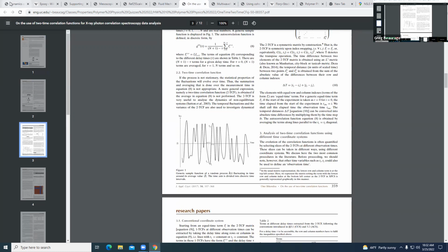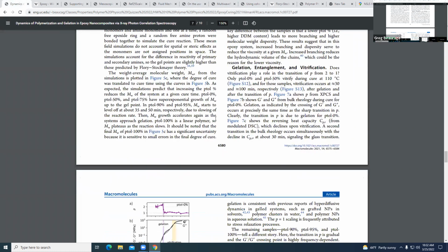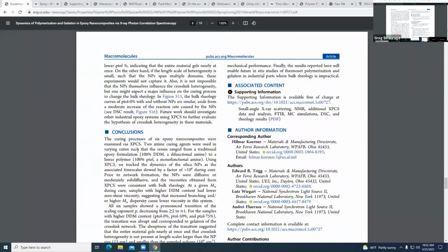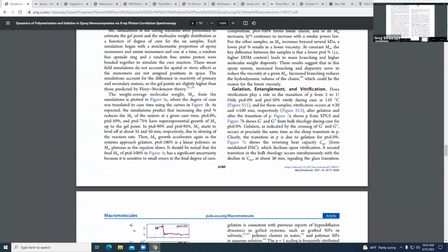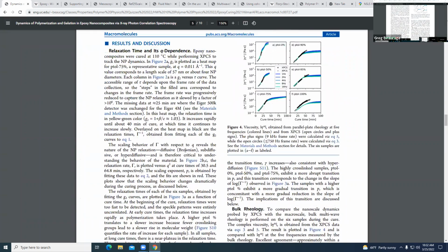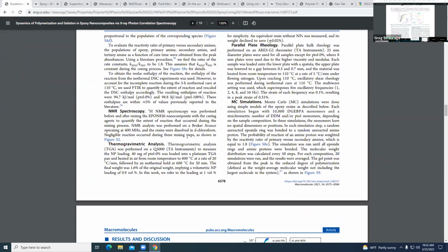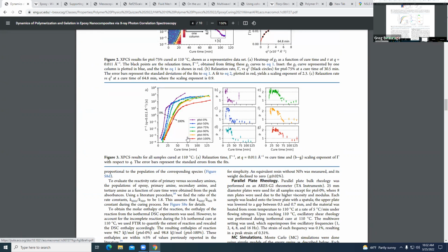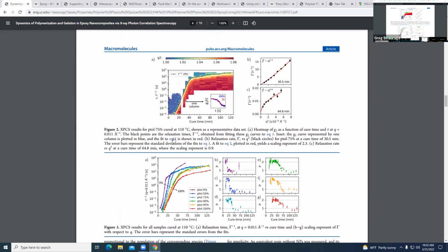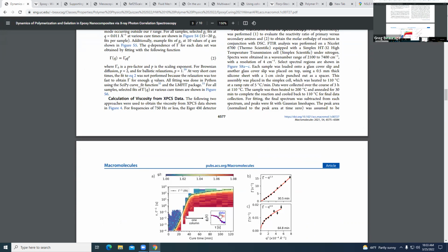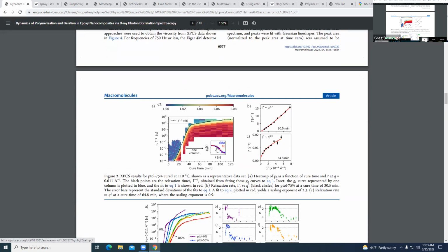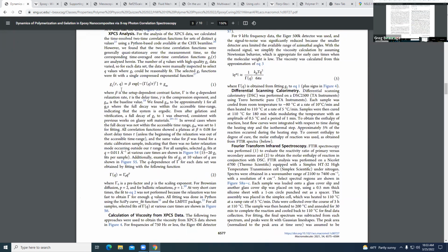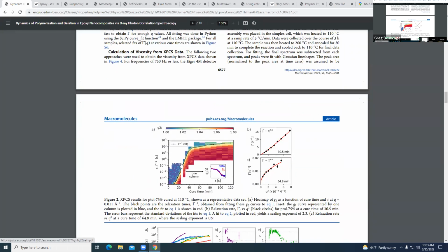So what he says in this paper is because it doesn't change over the time of the reaction, you can change it with the temperature. So he runs it at 110 C, which takes 2 hours for it to run, and his measurement's going to be like 3 minutes. Okay, and he does some measurements. He finds out that the decay pattern doesn't change. Oh, here he's got one of the decay patterns plotted in a small thing. So it's just this decay thing. In red is the fit to that kind of exponential decay. So anyway, it doesn't change over the time that he's measuring it.